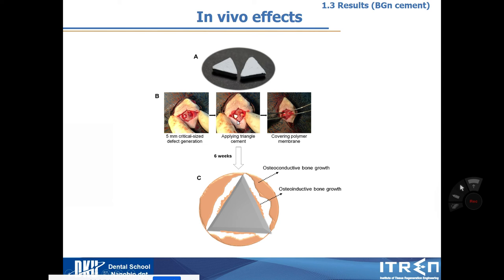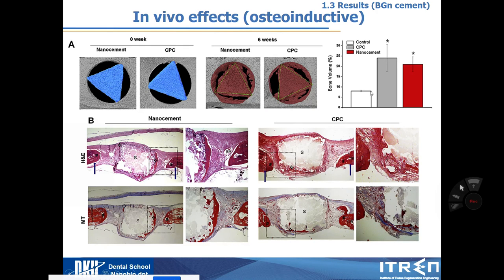Calvaria means the head bone. And then I saw similar bone volume formation in CPC and nano cement, but the only different thing is that nano cement can induce some bone formation from the material. But when you see the CPC, the original commercially available bone cement, the bone is always regenerated from the native bone. So you can say that this is called osteoinductive, when the material can start to induce bone or dentin formation from the side of the material. But when a certain material shows some regenerative potential of bone from the native bone, that is called osteoconductive.